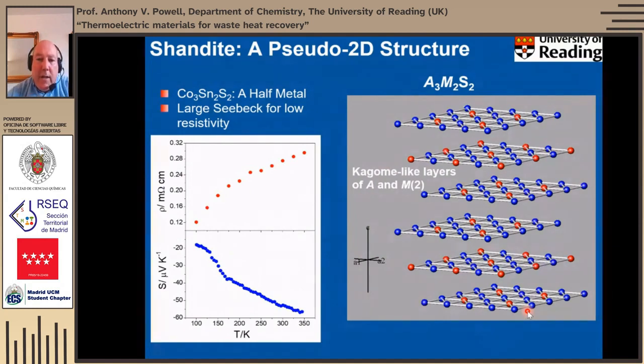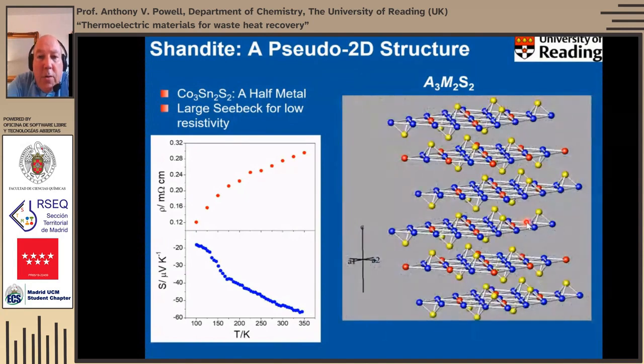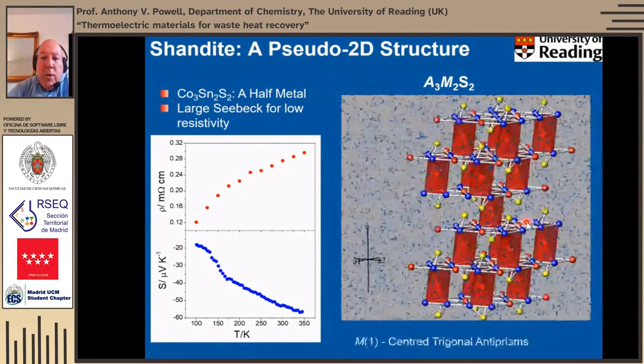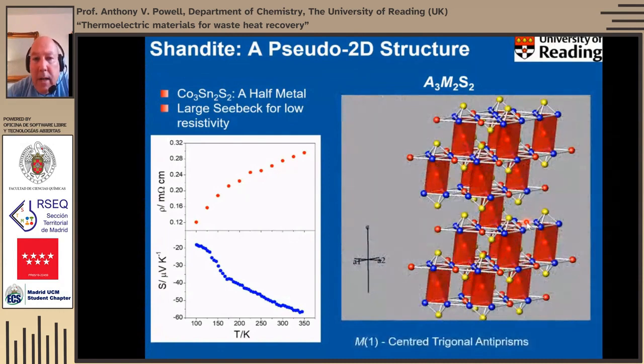It also has the attractive feature that although not low dimensional, it's pseudo low dimensional. So we have these Kagome-like layers here, these Kagome network type layers of cobalt and tin. The blue are the cobalt. So every Co3 triangle is then capped either above or below with a sulfur atom like that. Then the layers are joined together with a second tin atom, which is in a trigonal antiprismatic site. So we get this sort of pillared layer structure. So although not a true layered structure, it has low dimensional character.